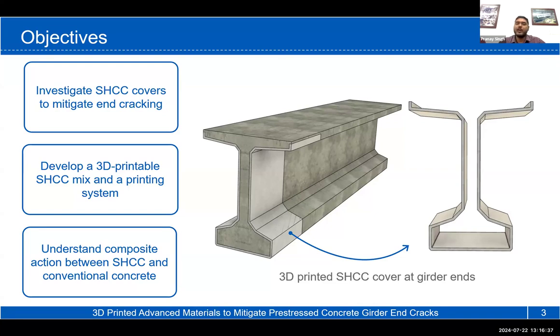So it is an optimized way of using advanced concrete material. So it is the same as you suggested. We are using a better concrete mix, but in an optimized way only at the surface. And this kind of idea is actually tested for beams, putting SHCC at the critical section where there is cracking. And people have observed that this SHCC as a cover helps in reducing or bridging those gaps. So this will be like a surface protective layer only, and it will prevent the exposure of the cracks to the environment so that deleterious agents cannot ingress, and the durability is not impacted much.